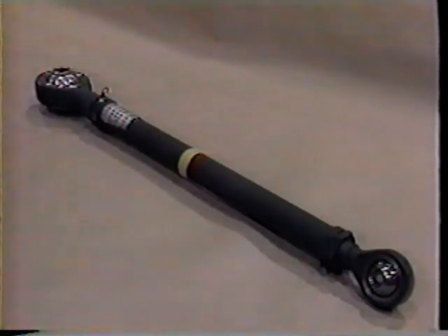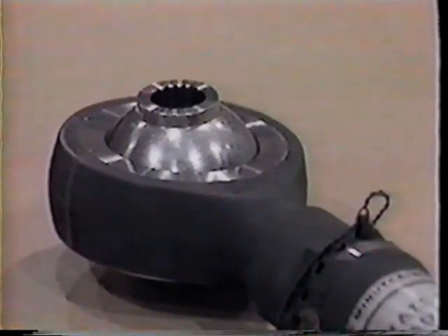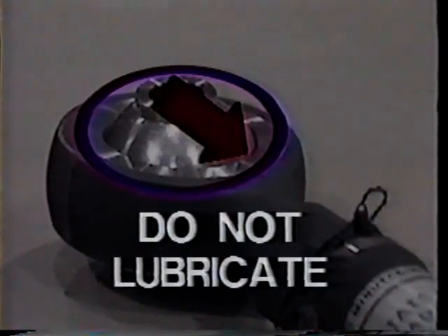Another area prone to corrosion is the spherical bearing. It's the exposed ball portion of the bearing that shows some surface corrosion. This surface corrosion takes the form of discoloration and eventual pitting. When corrosion forms, it's usually wiped away by the normal movements of the bearing. Because the bearing is lined with Teflon, lubrication or coating is not required. Do not lubricate or coat these bearings. This will actually damage the bearing.